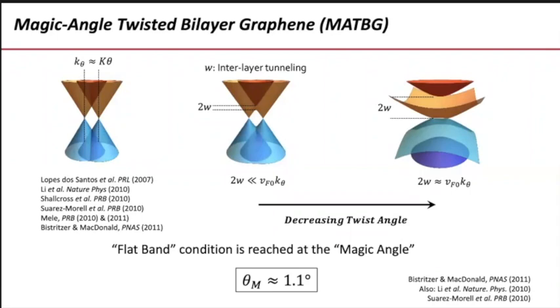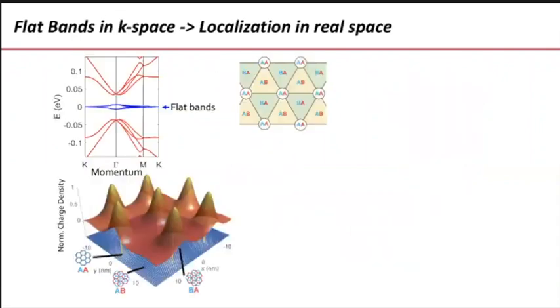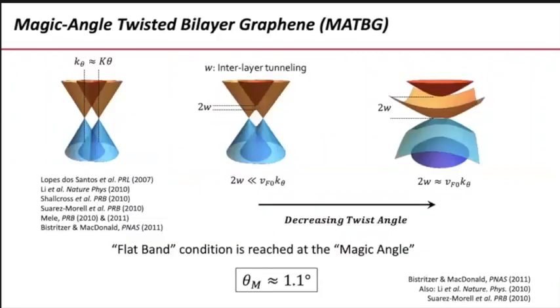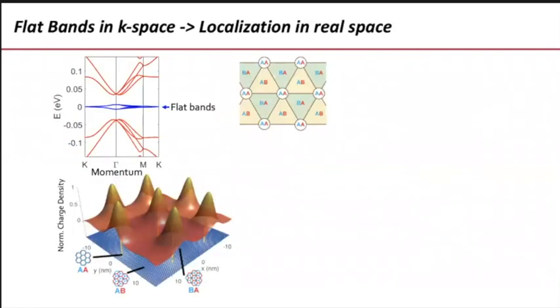Now, that was a cartoon; this is an actual calculation, for a given model, of the energy versus momentum for magic angle twisted bilayer graphene. You have these blue bands, which are the flat bands. These are the other remote bands, which are part of the folding process, the band structure that develops when you fold the bands because of the Moiré structure.